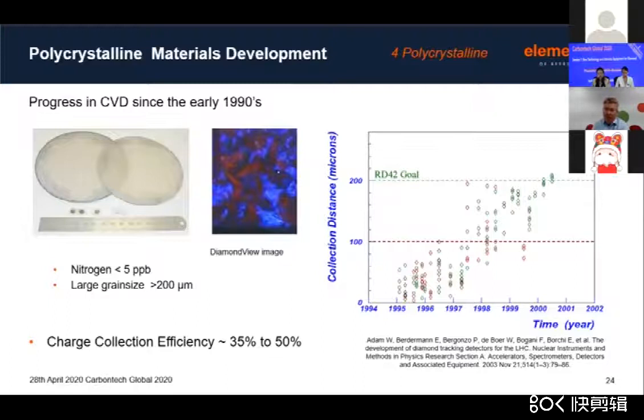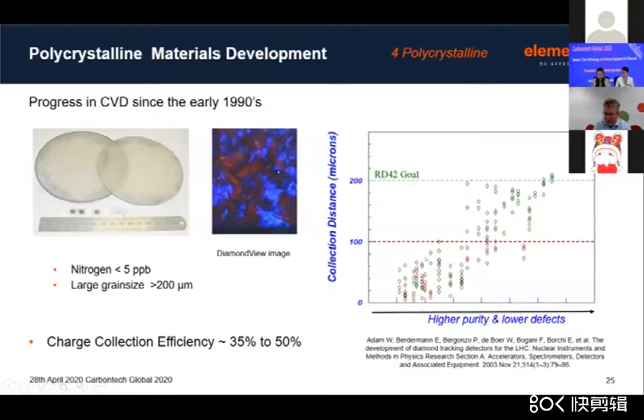We were developing these materials from the very early 1990s onwards, and it took us about 10 years to get through to this optimized material. What we found was that as we progressed, as we learned more about it, our purity of material was improving. We were able to get the nitrogen contamination in the materials down quite a long way, and we could also improve the extended defects and the grain size of these materials. But we reached a limit in these materials at around 200 microns of charge collection distance, which is around about the grain size of these polycrystalline electronic materials that we could make.